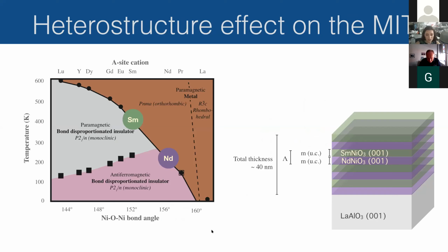So this is a study that we have done recently on superlattices of samarium nickelate and neodymium nickelate, which sit here and here in bulk. So they have different temperatures for their metal insulator transitions. So we make superlattices, just alternating one layer with another layer. And we keep the thickness of the two layers the same, M we call it, and we call the total periodic thickness lambda, or the wavelength lambda, and the total thickness we keep the same.